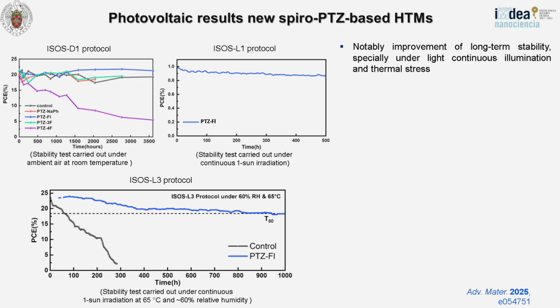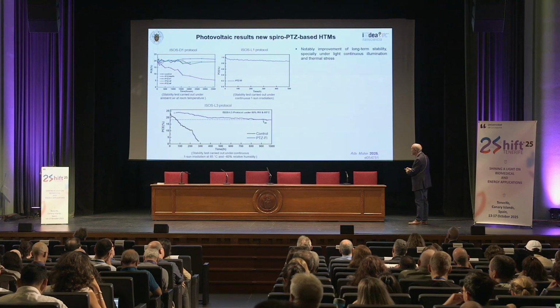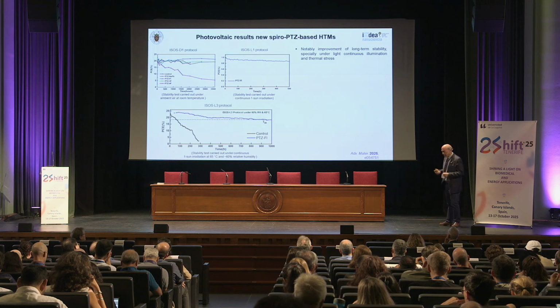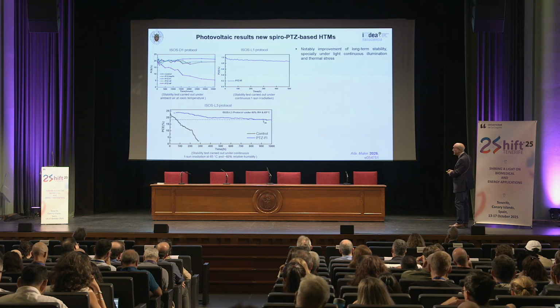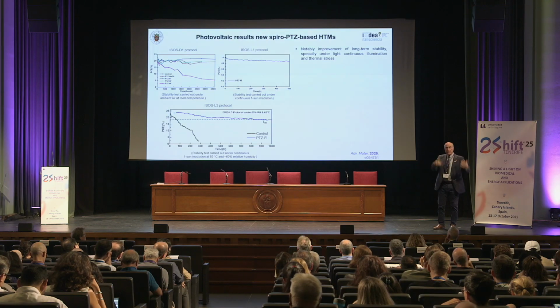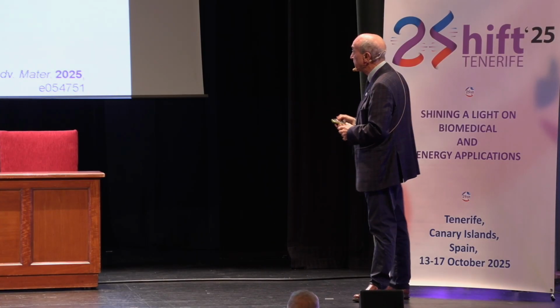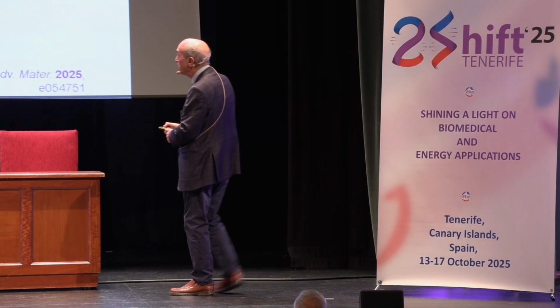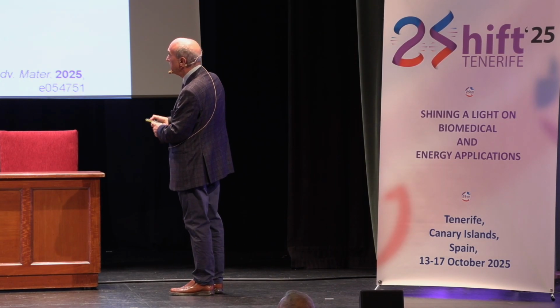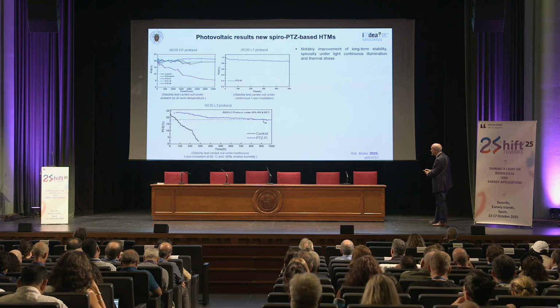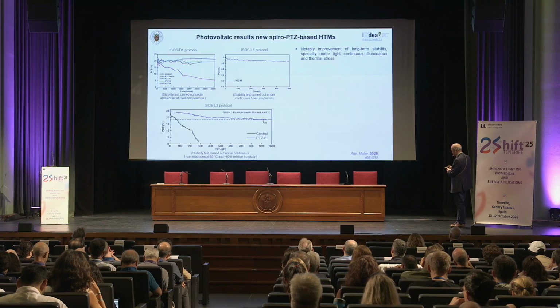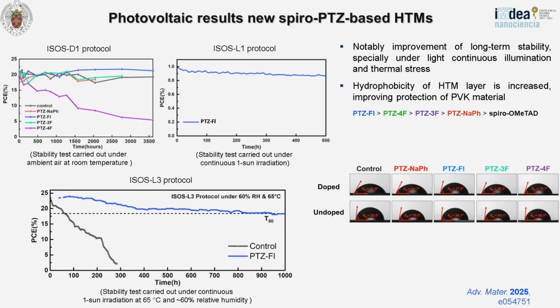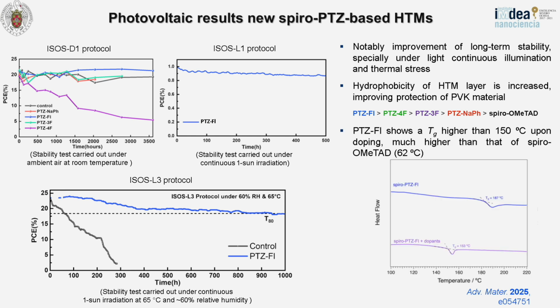So this is, again, the maximum power point tracking with 60% relative humidity and 65 degrees of temperature, which is expected in real conditions because of the heating of the sun. So this is just to compare what happened in this one, which was the fluorinated one, but the other one was really fantastic. The value is amazing. Many aspects. The hydrophobicity for this system was the best one. The naphthalene was also super.